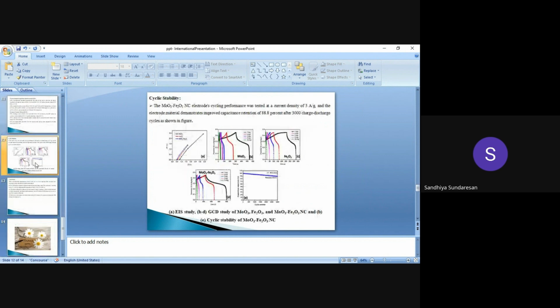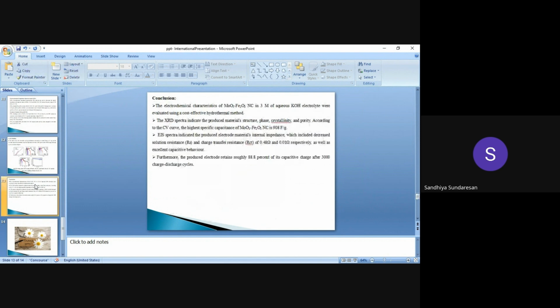This is the cyclic stability. The composite cycling performance was tested at a current density of 3 ampere per gram, and the electrode material demonstrated improved capacitance retention of 88.8% after 3000 charge-discharge cycles, shown in the figure. And this is the conclusion: the electrochemical characteristics of molybdenum dioxide and iron oxide nanocomposite in 3 molar aqueous KOH, potassium hydroxide electrolyte, were evaluated using a cost-effective hydrothermal method.